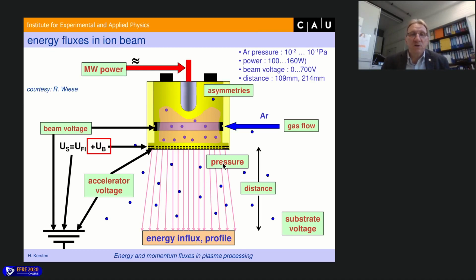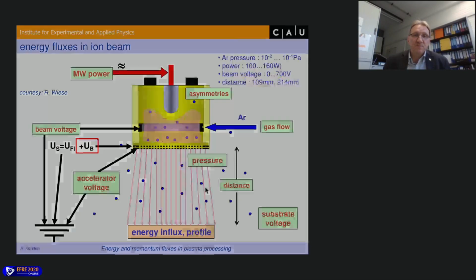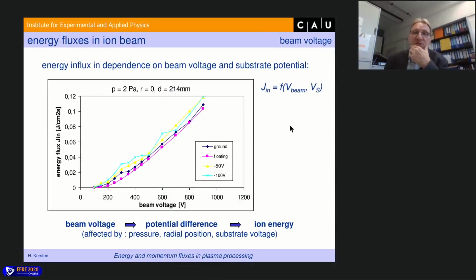And we can change a lot of parameters. For instance, we can change the beam voltage, we can change the pressure between source and probe, we can change the distance between source and probe, and we can give an additional substrate voltage, or we can change the incoupled microwave power, or we can change the gas flow, for instance. So here is the substrate which is treated by the ion beam, and we measured the energy influx at the position of the substrate.